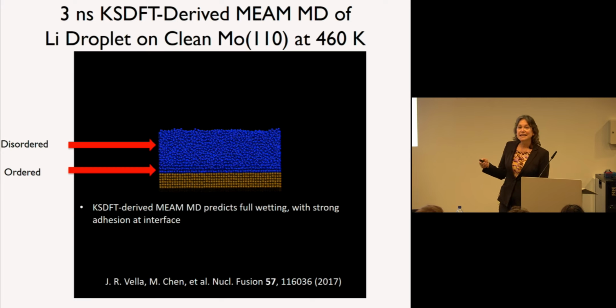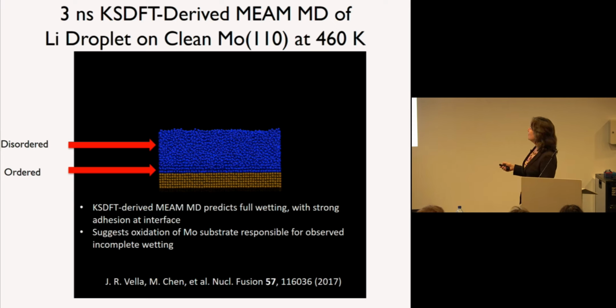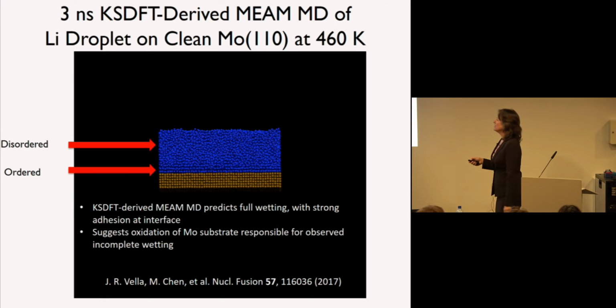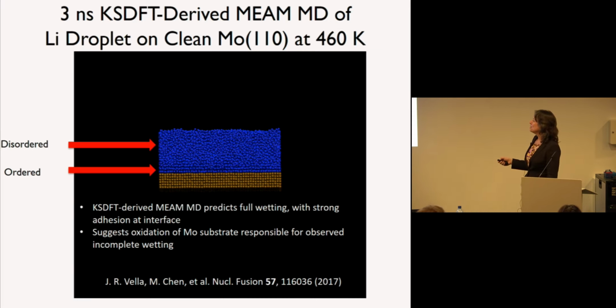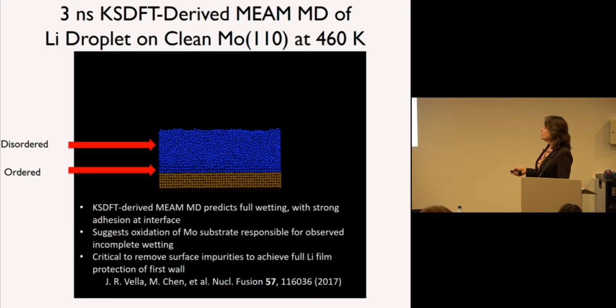Now it turns out experimentally they don't see it fully wet. So you have to, of course, be concerned that maybe the theory is just bad, okay? But we think that what is very likely is that there is, for sure, oxide on this surface, and that wherever there is oxide that hasn't been sputtered clean, that's probably responsible for the observed incomplete wetting, because we know under ultra-high vacuum conditions without oxide around that the lithium does bind strongly to the molybdenum. So this experiment that was done in the actual reactor to study wetting was done under conditions where there was oxygen around. So what it says is it's critical to remove surface impurities to get full lithium film protection of the first wall.